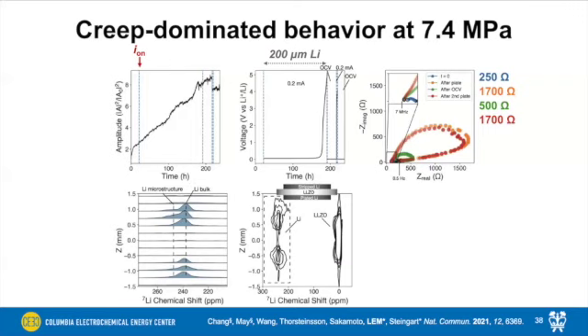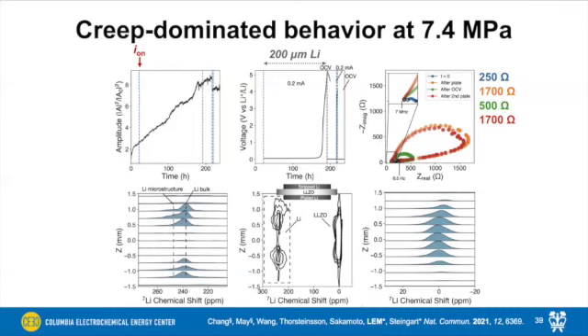When we take a look at our impedance data, we see something very similar at the beginning of cell assembly, which is expected, but we actually see much better recovery between our two plating steps. So they're almost in perfect agreement between our first and second plating step, which indicates that we likely have much better interfacial contact, but we've likely also formed a much better chemical interface as well. And whenever we take a look at what's going on chemically at this interface with our chemical shift imaging experiment, that's exactly what we see here. So we don't actually see any species at this higher frequency near 20 ppm. We only see things that correspond to LLZO and LLZO decomposition products that are solid ion conductors. So things that would not be quite as detrimental to the interface.